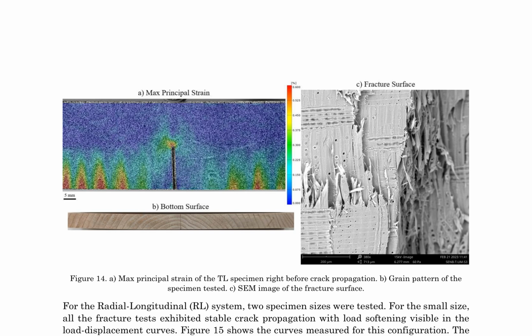In the radial-longitudinal (RL) system, fracture tests were conducted on two distinct specimen sizes. The smaller size exhibited stable crack propagation with load softening, as evident in the load displacement curves, figure 15. These curves, adjusted for elastic displacement, were accurately fitted by the decay function, enabling the extrapolation of total fracture energy. This approach provided a reliable estimation of both G_F and G_f for all tests.